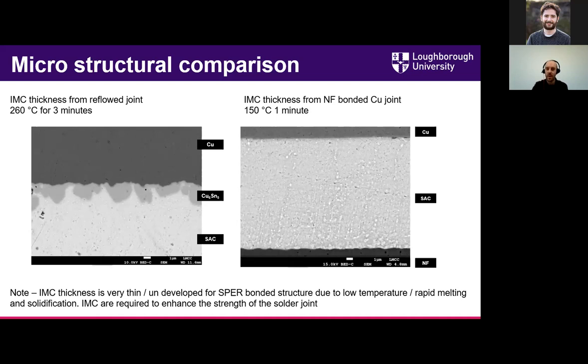And this gives us a great opportunity to look at thermal aging and how those intermetallics grow from no intermetallics or very small intermetallics all the way up to fully formed intermetallics. And on this side is just an example of what a normal solder joint would look like compared to a nanofoil bonded joint.